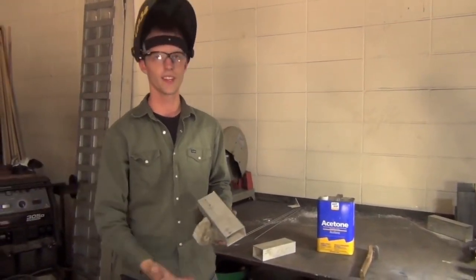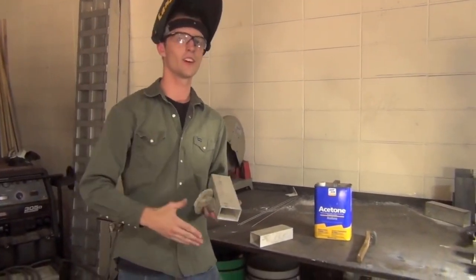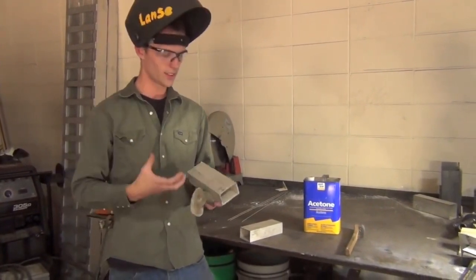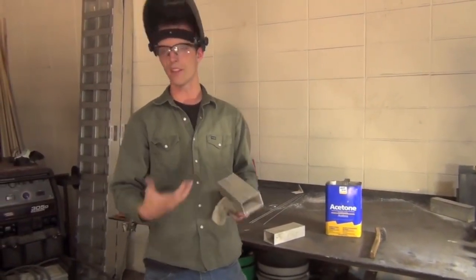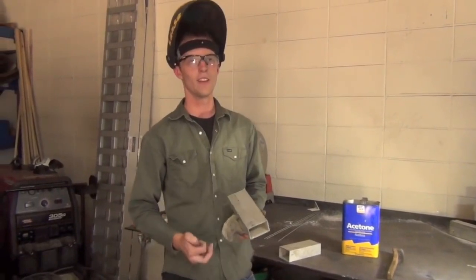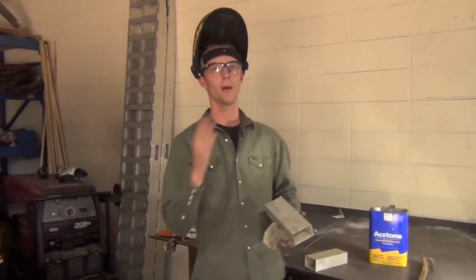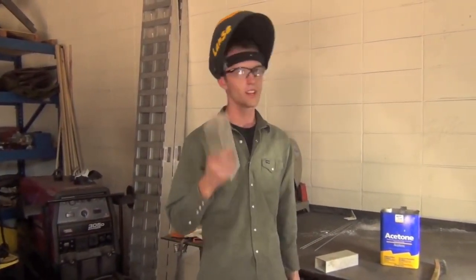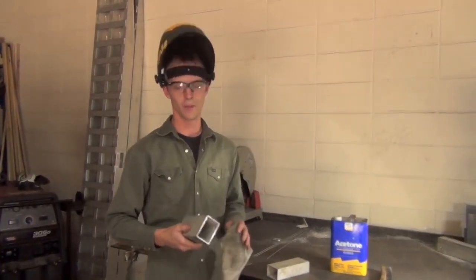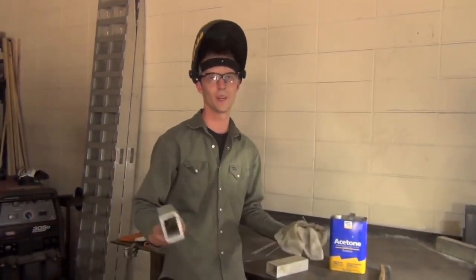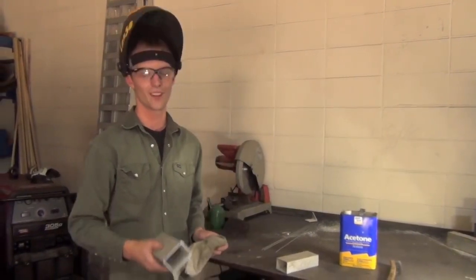With AC TIG, the alternating current, it's called cathodic bombardment. It basically blasts this layer into nothing. And one of the advantages of TIG welding aluminum is you can control how much cleaning action or how much penetration you're getting. But you always want to clean your material to the best of your abilities in that given situation. I mean, we all know you can't get everything 100% clean all the way.